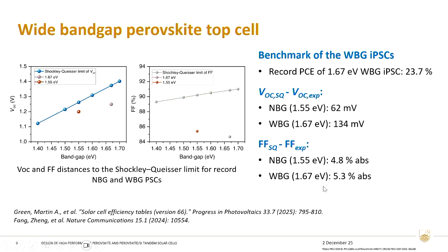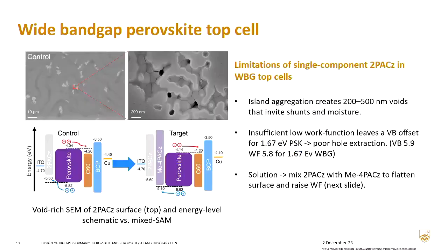In terms of fill factor, for the wider bandgap perovskite there are rare reports showing a fill factor above 0.85, but there are a handful of reports showing a fill factor of low bandgap perovskite above 0.86, some of them achieving 0.87, which is very beautiful. So although there has been a lot of progress in recent years for wide-bandgap perovskite, there is still a lot of room to further improve.